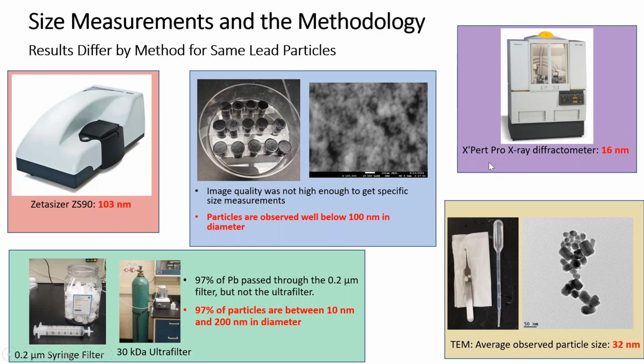X-ray diffraction actually tells you something about the crystalline size. If you look at the peaks and the width of the peaks, you can get information about the crystallite size. X-ray diffraction told us that those particles were 16 nanometers in size. Our syringe filter, ultrafilter approach tells us that 97% of the particles are between 10 nanometers and 200 nanometers. That's about the best we can do there, so we don't get specifics. And then TEM is an instrument that gives us really small particles, and here they are. We can take these images and do some graphic analysis using imaging software, and we come up with an average size of 32 nanometers.